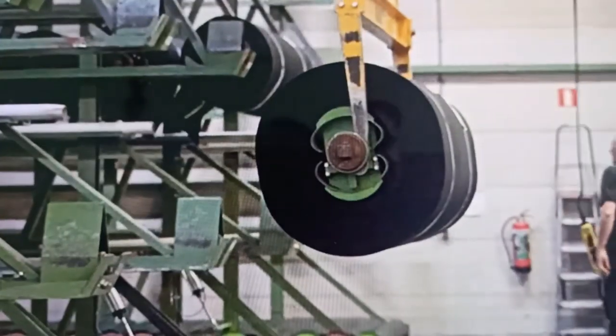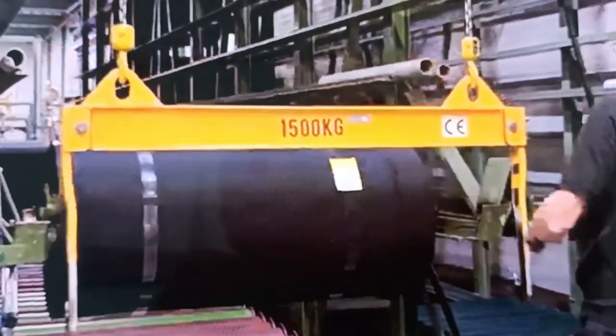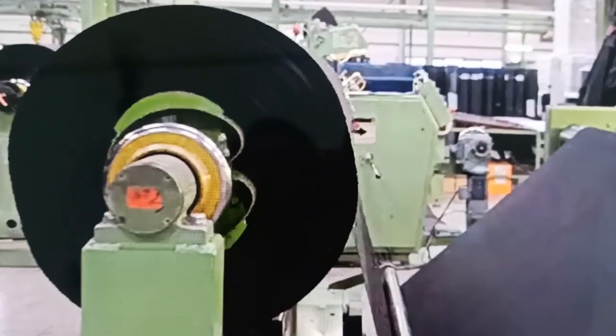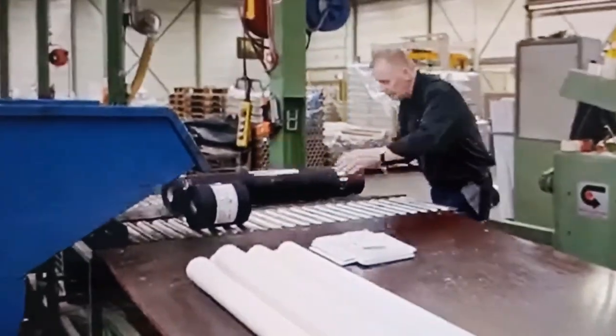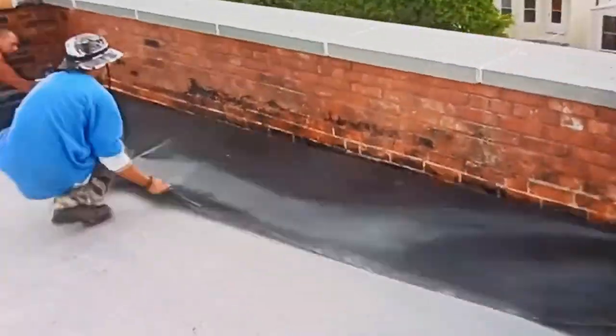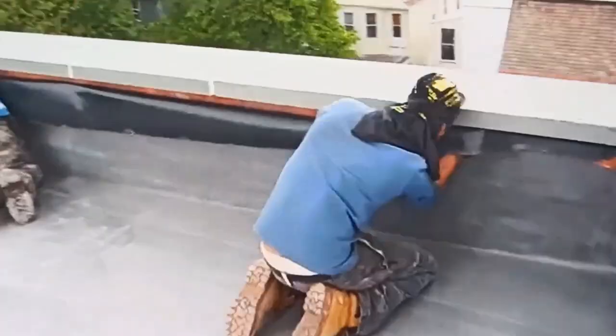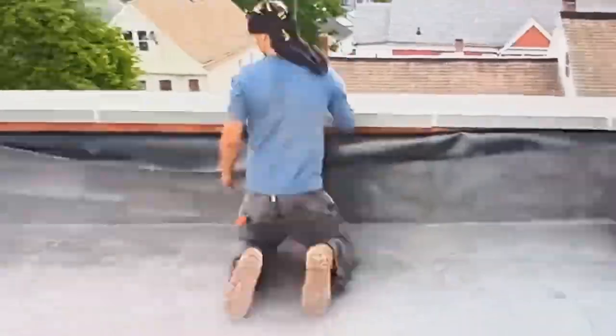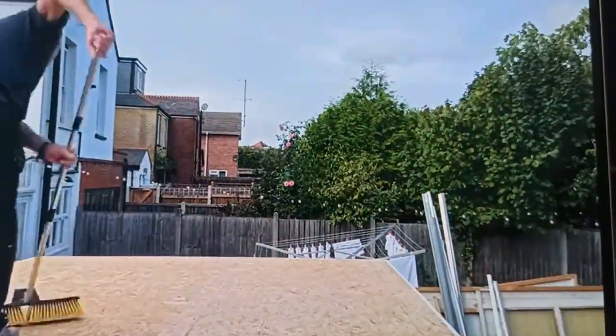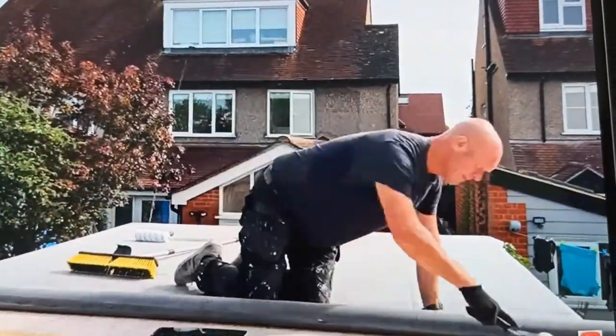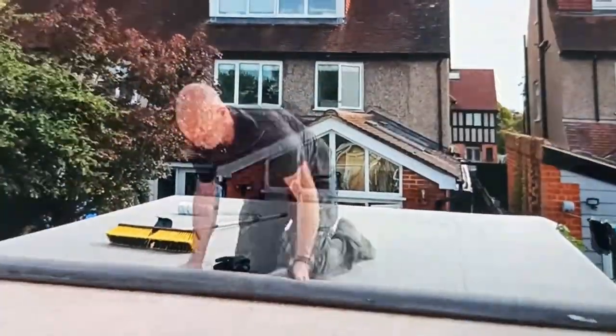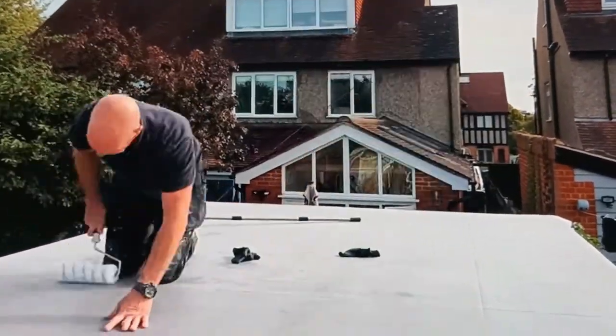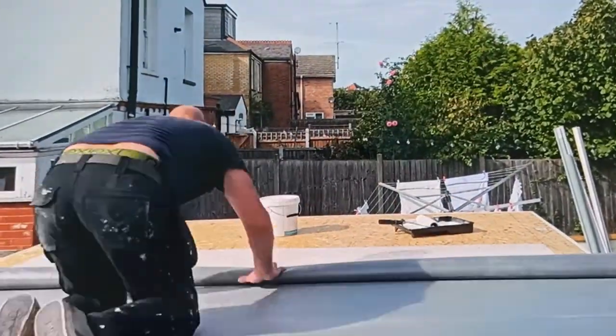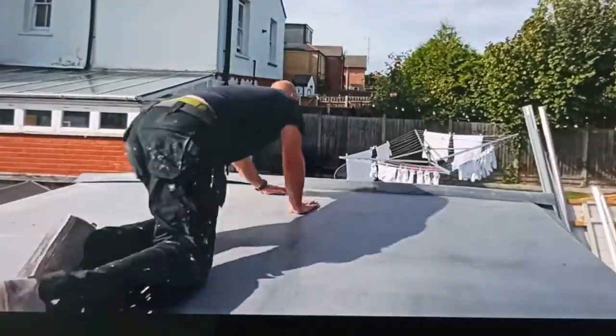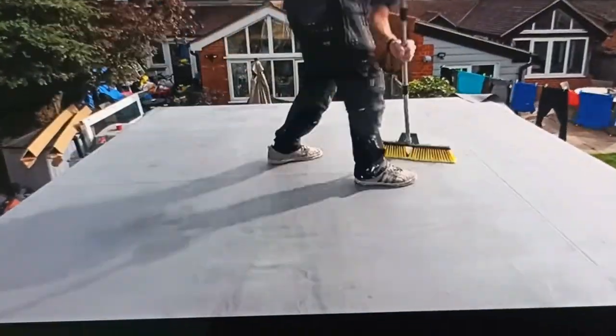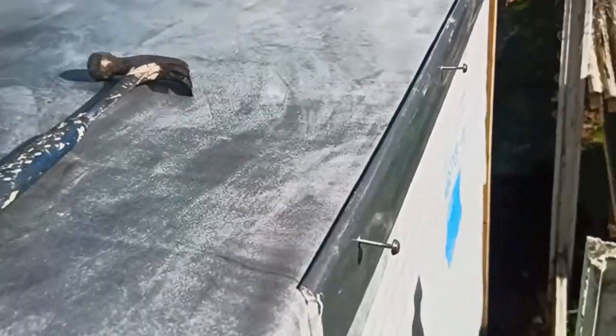ASTM specifications. To ensure the quality of EPDM roofing membranes, they must meet the ASTM specifications: ASTM D4637, ASTM D297 for chemical analysis, ASTM D412 for physical properties, ASTM D1149 for ozone resistance test, ASTM D471 for water absorption test, and ASTM D573 for heat resistance test. Some of the specifications are principal polymer EPDM above 95%, tensile strength 9 megapascal, elongation at break 300%, hardness 65 plus or minus 5 Shore A, brittleness point minus 45 degrees centigrade. By following these specifications, manufacturers can ensure that their EPDM roofing membranes meet the highest standards of quality and performance.